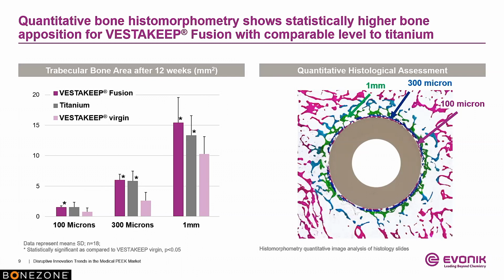So we take a look at the staining here. You see the implant. There's a hole in the implant to facilitate biomechanical pull-out testing. Based on the diameter of the implant, we measured at 100 microns, 300 microns, and 1 millimeter, and were able to assess what that trabecular bone area looked like at both the 6 and the 12 week time points. And the numbers we're seeing here are at the 12 week time point.